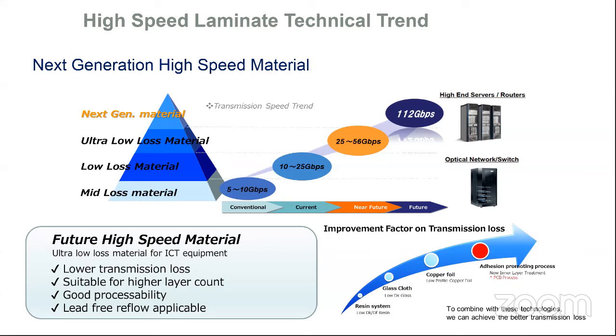The older systems, when you say epoxies tend to stick to everything. They're not really a problem. It's the high functionality, high speed, low loss materials that are not necessarily an epoxy. They could be an epoxy blend, but now we're relying on less mechanical adhesion properties and more of a compatibility from a chemical standpoint, where we have silane coupling agents or different treatments from different chemical suppliers that have an affinity for improving the wet out of the high speed, low loss resin systems to itself. So that's really where our focus needs to be. Interesting. All right. Well, thank you.